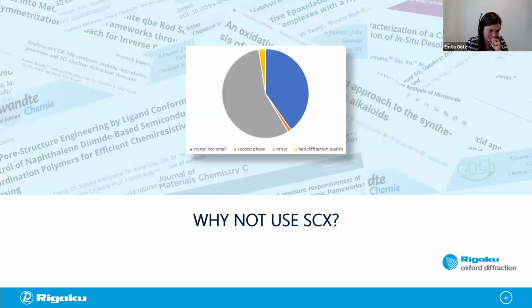So now we come to probably the biggest question for measuring with the Synergy-ED, because why couldn't we just use X-rays? And while for a lot of the samples, the reason was not clearly defined in the publications, the biggest issue, and I guess this also counts for a lot of the undescribed reasons, is that the crystals were simply too small to be measured with single crystal X-ray diffraction.